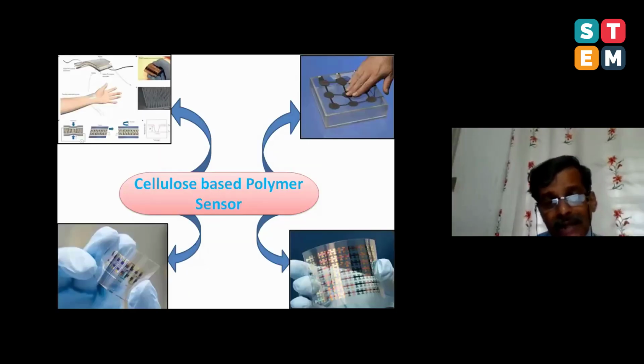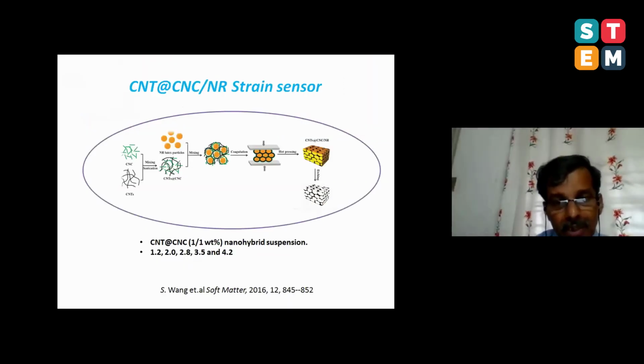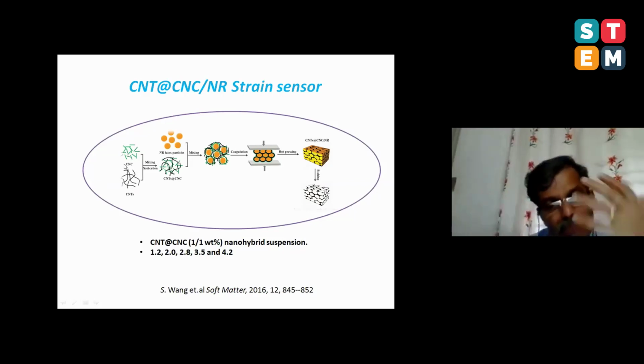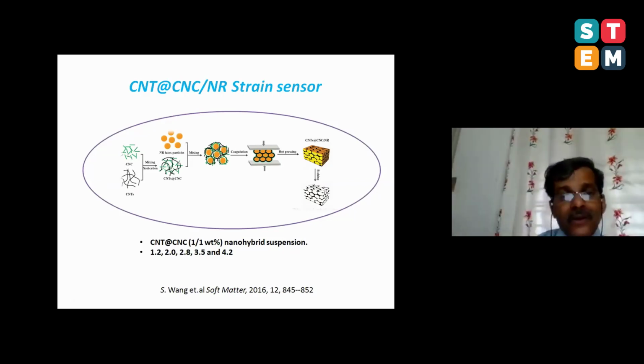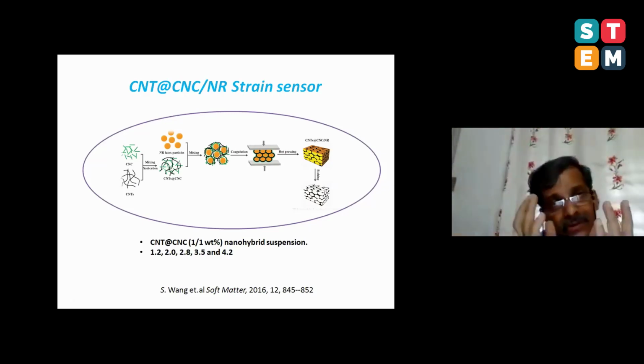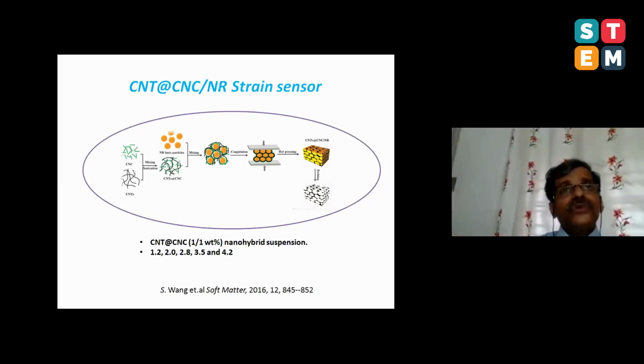Let me show you on the slide where we can make beautiful sensors. I will show you a slide from the work of Professor Mann's group. What they did is they made a hybrid of nanocellulose and CNT together. They mixed nanocellulose and CNT to make hybrids, and then mixed with the natural rubber latex. And eventually they made a beautiful nanocomposite of natural rubber matrix filled with nanocellulose and carbon nanotube. You know the beauty of this?